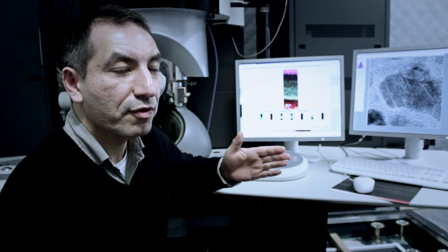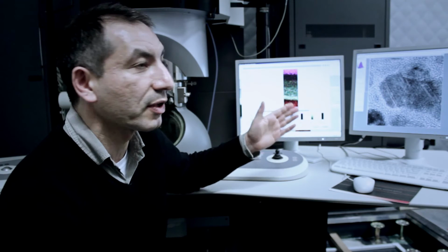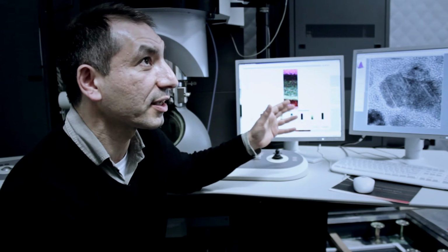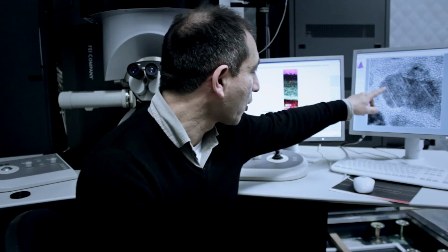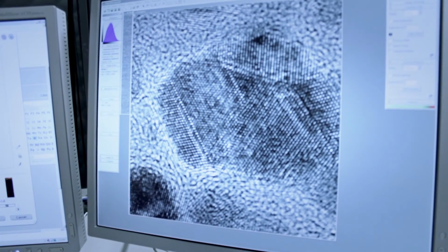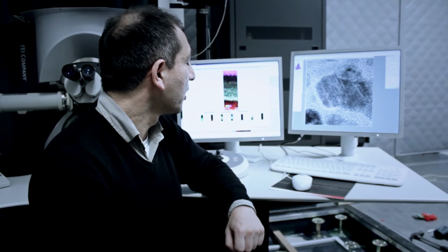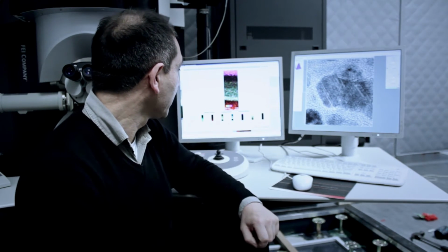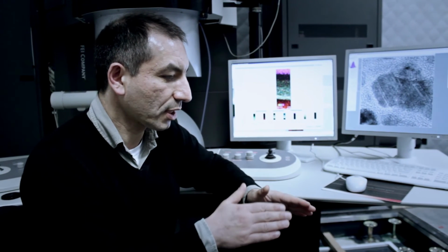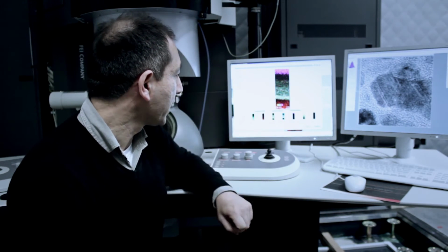This is a FEI Titan, aberration corrected. And what we have is an ability to go from 200 to 90 kV, which is important if you want to look at materials that can get damaged by high voltage. Very high resolution, atomic resolution, so you can see here, this is gold lattice images that you can see of the gold atoms. And we also have a four-quadrant EDS detector, where it allows us to get really high capture angle for chemical analysis, so very high amount of counts we can get. So we can get really high resolution chemical analysis into atomic resolution.